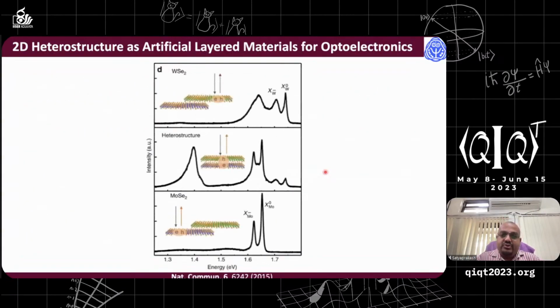For example, here I'm showing you a result of low temperature photoluminescence of stacking two different materials, molybdenum selenide and tungsten selenide. You can see the photoluminescence measured at very low temperature. This is done on individual MoSe2, and this is the spectrum coming out of that. When you do this purely on WSe2, this is the spectrum that one would get. But from the heterostructure, you see a drastic new peak emerging, which is basically the interlayer exciton. So these are very interesting phenomena happening in this layer heterostructuring of 2D material.